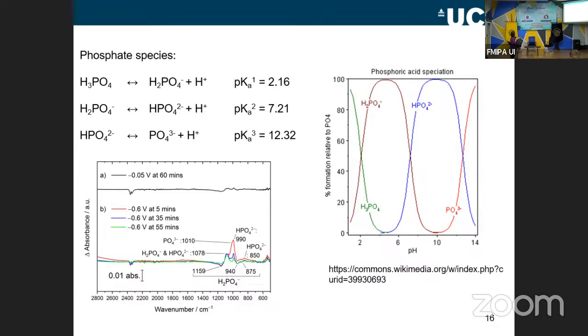So if we start with the most acidic solution, up here, we have phosphoric acid, H3PO4, and this can lose a proton to give H2PO4-, and the pKa for that process is 2.16. So that's under acidic conditions. Then the H2PO4- can also lose a proton to give HPO4 2-, and this has a pKa of 7.21. So this is kind of the composition that we use to make up our pH 6.8 solution. It's a solution that contains about equal amounts of the H2PO4- and the HPO4 2-. Then if we go to more alkaline conditions, what we can see is the HPO4 2- can lose another proton to give this phosphate species, PO4 3-, and the pKa of that is 12.32.